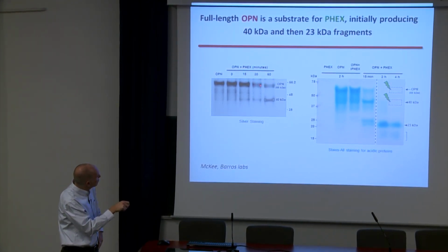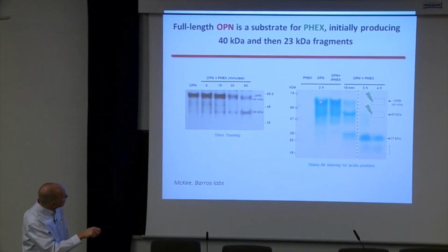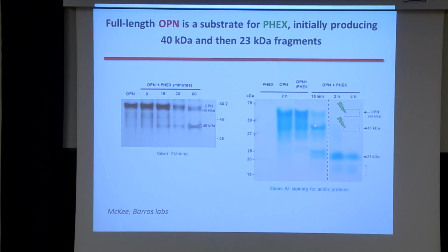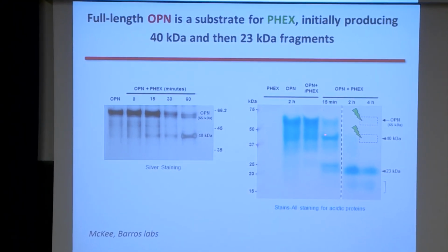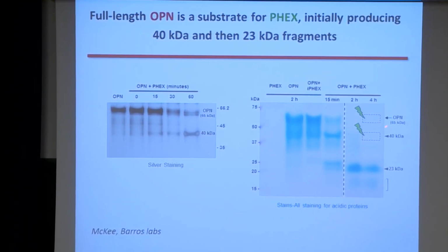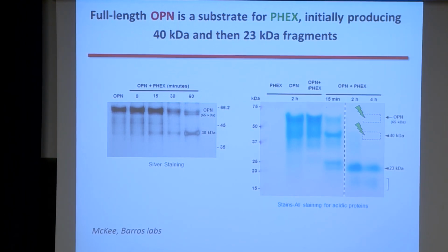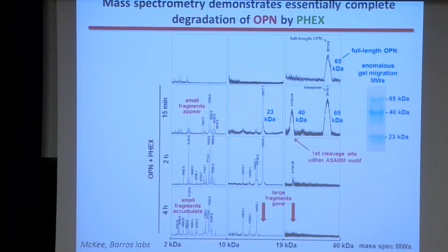This is how you show degradation studies. New bands accumulate lower, degrade it with PHEX. New bands go lower. You can add inhibitors. And finally, by 4 hours, full native length OPN was cleaved into these smaller fragments. So we were able to identify not just its peptides, but the full-length osteopontin protein as a substrate.